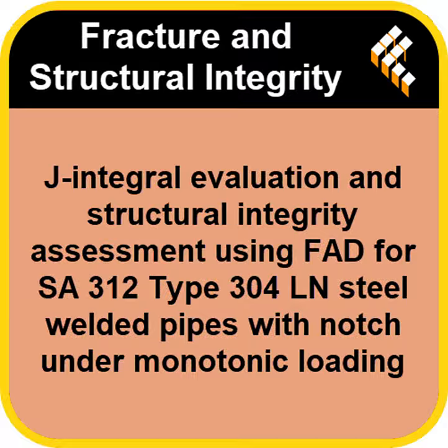They then plotted all these calculated assessment points, LR, KR, against standardized safety lines, the failure assessment lines, the FAL. They specifically used lines based on the SINTAP procedure and also the BS7910 standard. Are those lines very different? The results showed the failure assessment lines from these different standards actually yielded quite similar boundaries in this case. But it's important to note that BS7910 offers different levels, and Level 2B provides a material-specific line derived from the material stress strain curve, which is generally considered the most precise way to define that safety boundary.